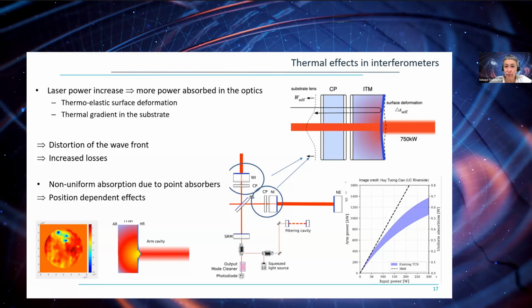So there are two thermal effects. One, which is due to the absorption in the substrate, induces a thermal gradient and a lens. And the other is due to the absorption into the surface of the input test masses, which induces a change of radius of curvature. The most effect is in the input test masses, as these are the test masses which see more power because they are inside the Fabry-Perot, and the beam goes through those test masses.